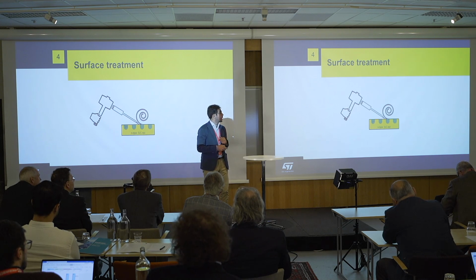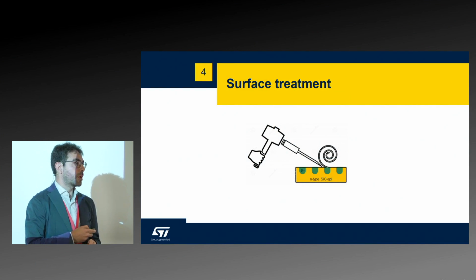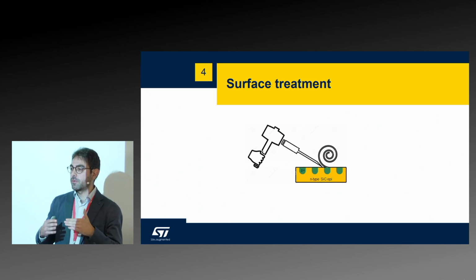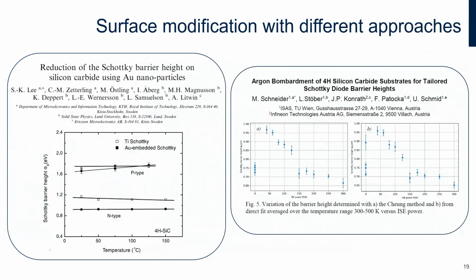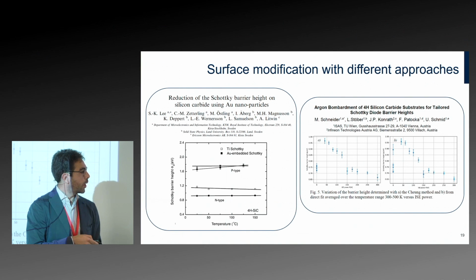And the last topic is that we are now interested in surface treatment because, again, Schottky barrier height is a matter of surface. So I just picked two papers, one from a Swedish group that put gold nanoparticles on top of silicon carbide, and they observed a lowering of the Schottky barrier height for the gold nanoparticles deposited on SiC. And it's really interesting also because they can modulate it by controlling the size of the gold nanoparticles. And this is a paper from our colleagues from Infineon in which they modify the surface by sputtering argon on the surface, and they can again modulate the barrier height.